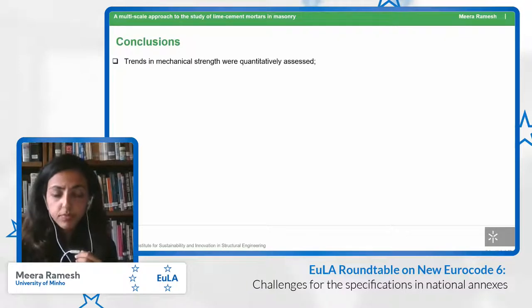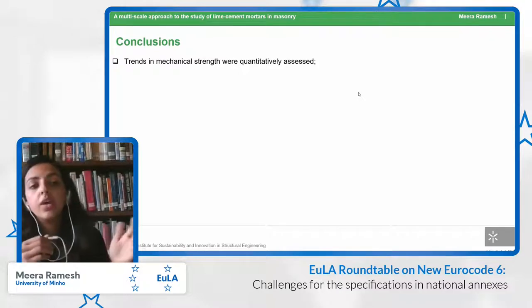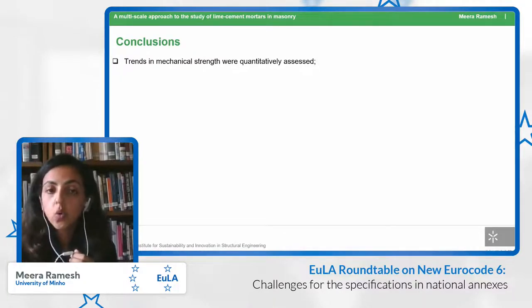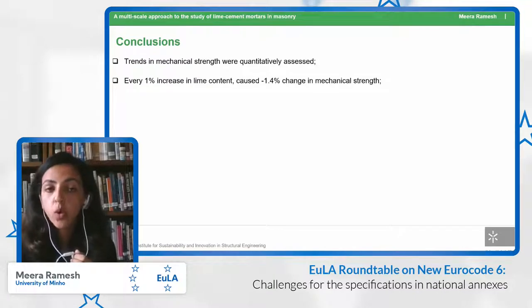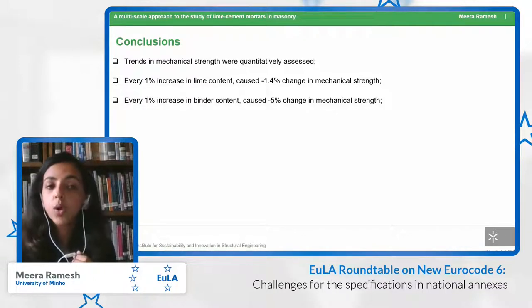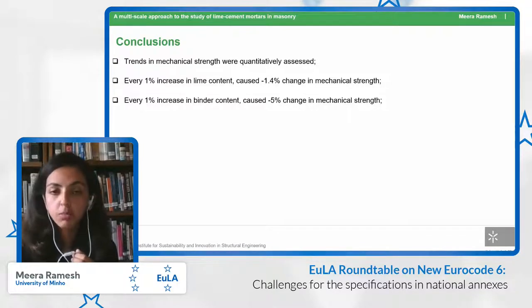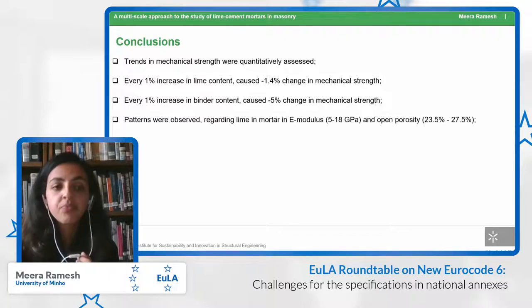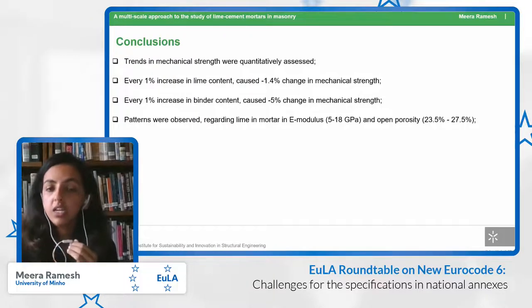So to conclude, what we have shown you in this presentation is that we assessed the trends in mechanical strength quantitatively. We found that for every 1% increase in lime content, there was approximately a 1.4% change in strength at the mortar level. For every 1% increase in the binder aggregate ratio, there was approximately a 5% reduction in mechanical strength of the mortar. And we obtained consistent patterns in Young's modulus and open porosity as you changed the quantity of lime in the binder.